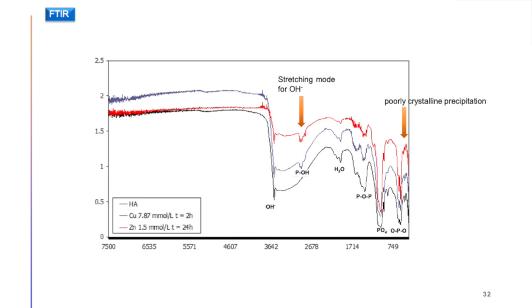And then we studied our solid samples with infrared spectroscopy to understand the position of the different ions, again compared with the hydroxyapatite, and you can see they are quite similar. We observe this shoulder that is due to the presence of a poorly crystalline material, and this one here that is the POH group, in particular meaning that the metals could substitute this group, but then the other positions are quite similar. They don't show great difference.